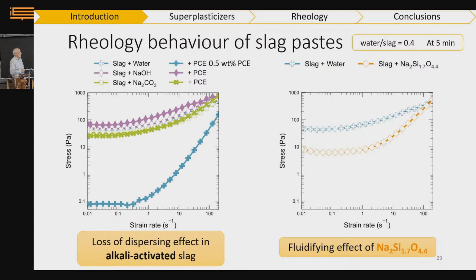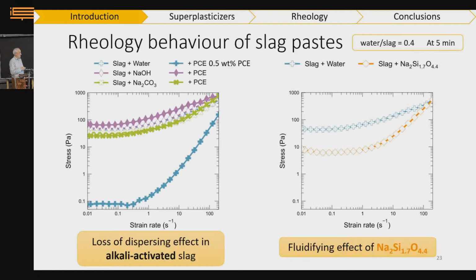If I use another activator, which is sodium silicate, very commonly used in industry, the situation is a little different, so I won't talk about it right now. I reserve that for later on in my talk, because you see that already silicate anions have a dispersing effect, they tend to deaggregate powders. It's very well known in clays, for instance. So the yield stress issue is not as strong when we are dealing with sodium silicate activation. So I will focus, for the beginning, on hydroxide and carbonate activation.